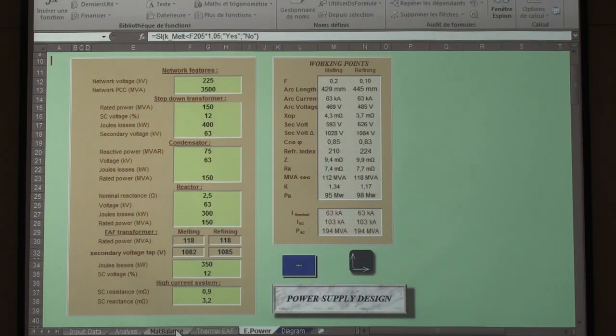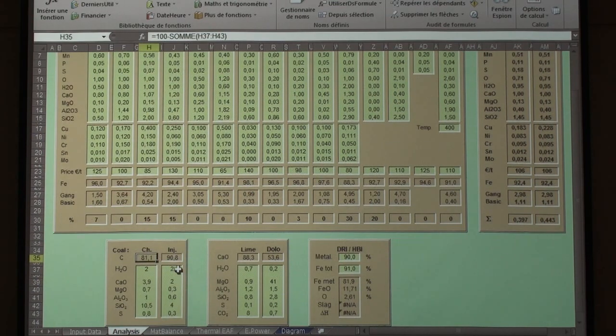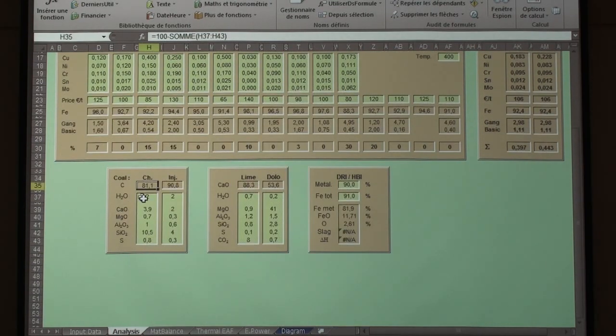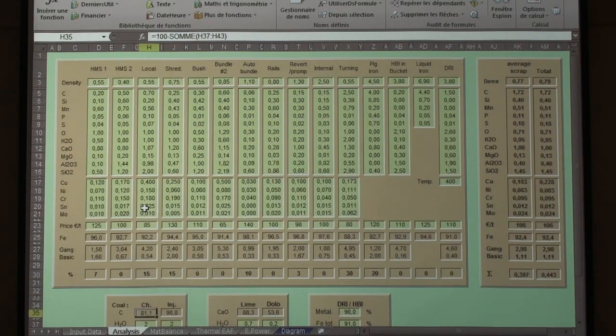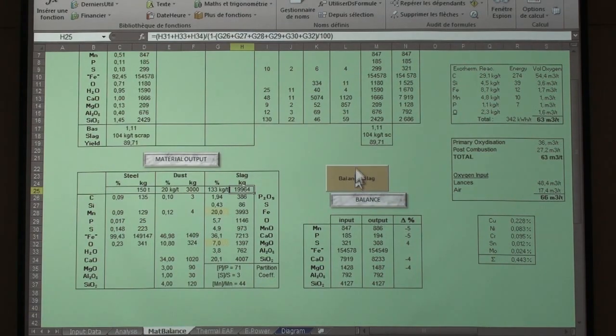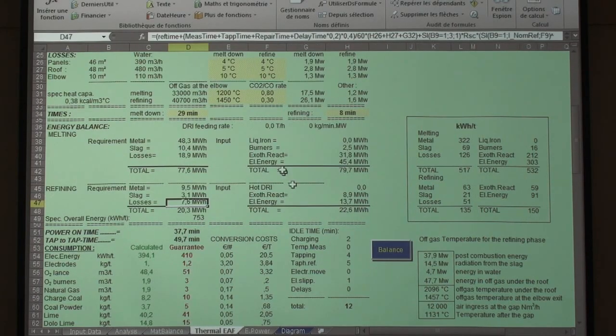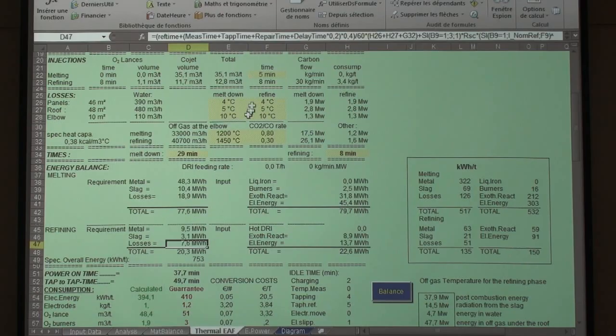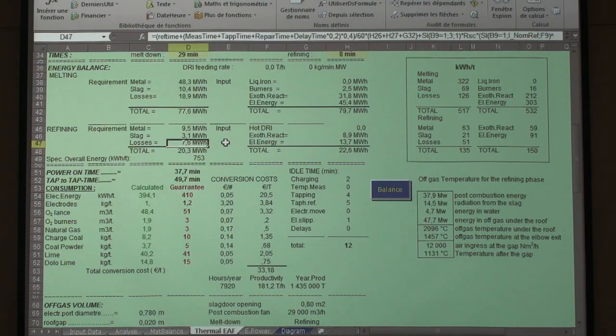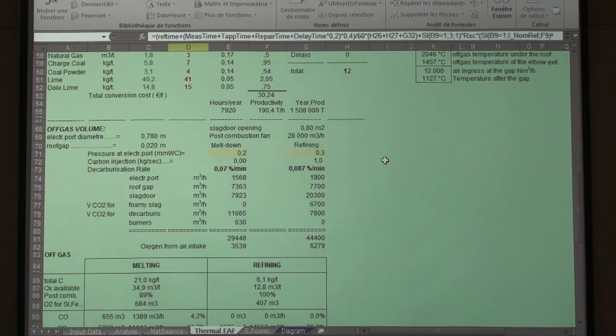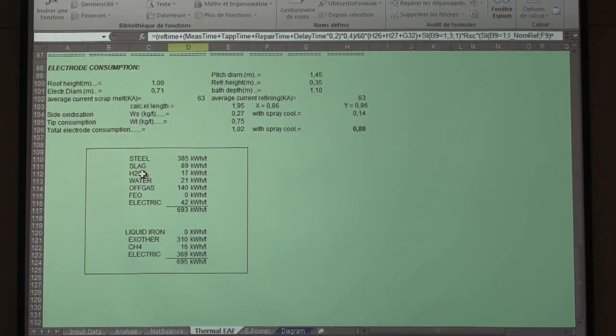Then you go to analysis. You adapt the analysis of the fluxes whenever it's necessary. Eventually, you adapt the scrap analysis depending on the situation. You check the material balance. You adjust the iron content and the magnesia you need. And then thermal balance. You adjust the water delta T and off-gas temperature. You balance and you check here on the Sankey diagram.